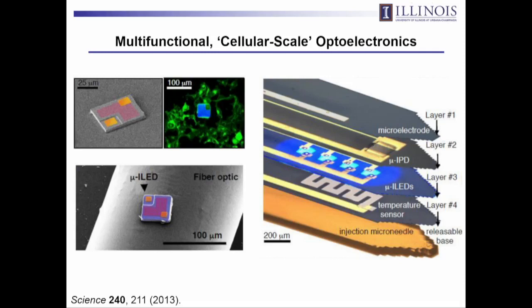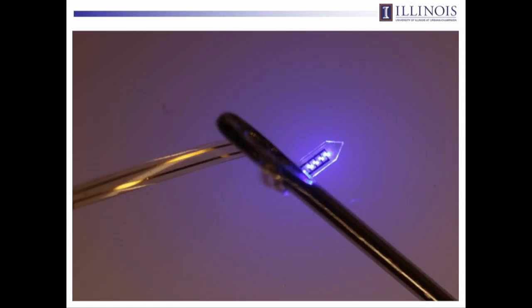And even after you've stacked up all of these layers, you still end up with a platform that's a small fraction of the diameter of the optical fiber in terms of total thickness, only maybe 25 microns or so. In fact, so thin that it doesn't even offer the kind of mechanical rigidity that you need to penetrate into the brain. You try to penetrate into the brain, it just buckles. So what we have to do is we use a bioresorbable adhesive to mount this thing on a thicker injection microneedle to provide the stiffness. And then once the thing is inserted in, we pull the injection needle out, leaving the optoelectronics behind in the brain.